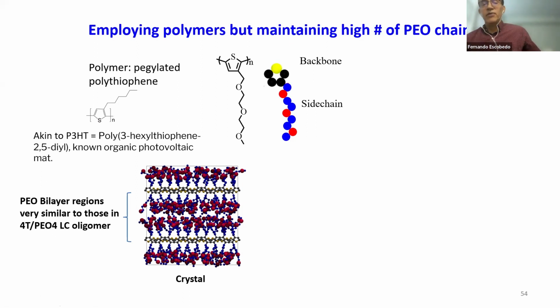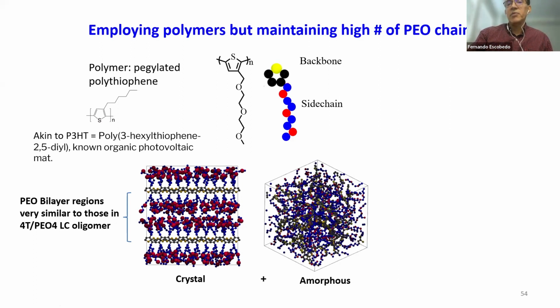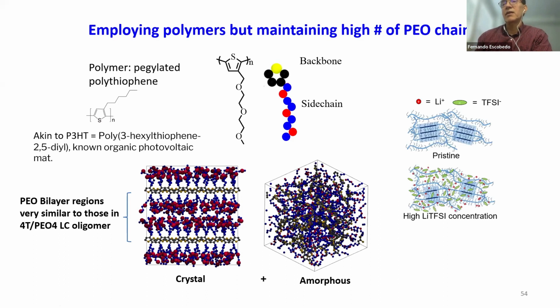Now, the problem with the polymer, for different reasons, is that this system relaxes more slowly, and they are prone to kinetic traps, and you have more polydispersity, so you don't just get this crystalline state, but you also get an amorphous state. In fact, our best understanding is that what you form is really a semi-crystalline material. We have these domains of crystallites embedded in some kind of matrix of amorphous material. That complicates a lot the characterization and the interpretation of results from experiments, but also from simulations. So we did not attempt to model something that contains both, but study systems which are either 100% crystal or 100% amorphous, and try to learn lessons from there to then extrapolate to what will happen if you have mixtures of both.